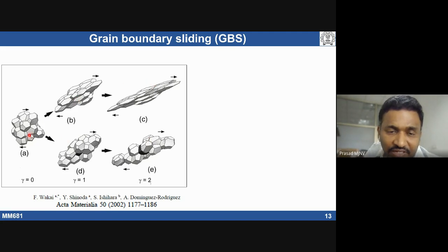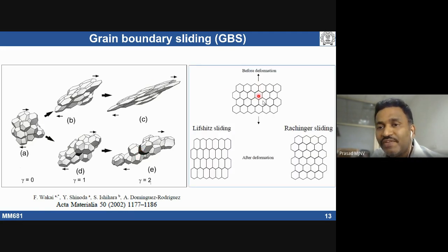So at the end of the superplastic deformation, if there is a shape change in the grain structure, then it is called Lifshitz sliding. If there is no shape change, but, as I showed, very large elongations, that mechanism is called Rachinger sliding. So if initial grains are like this and it is showing elongated grains, but it has undergone sliding, this is called Lifshitz sliding. If there is no shape change, but the material has shown a significant amount of strain, that is called Rachinger sliding.